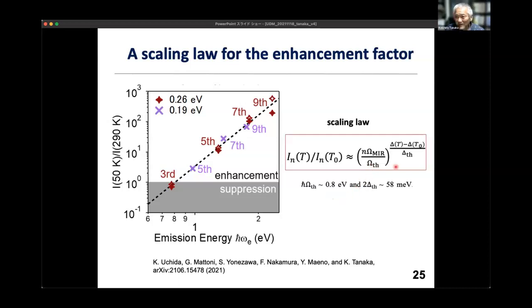And interestingly, this parameter is 0.8 eV, and this one is 58 milli-electron volt. This one is very close to the band gap energy at low temperature. But we don't know this. What is this 58 milli-electron volt?